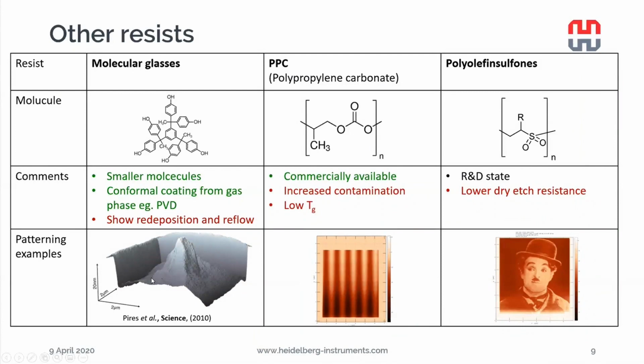the material starts to reflow and basically fill back up this pattern and is not stable over time. There have been polypropylene carbonates that also show increased contamination and also have a low glass transition temperature where we have this melting issue and smearing.